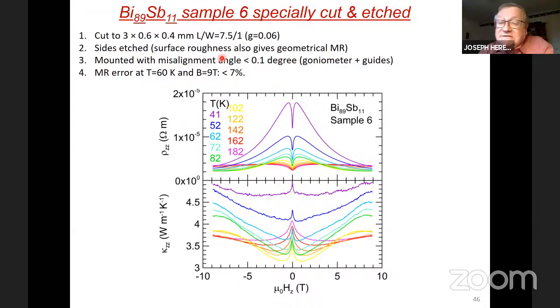And so our little error estimation routine then gives us at 60 Kelvin an error that is of the order of 5%, certainly less than 7% would correspond to this, which is a worst case scenario. And then he managed to measure on the same sample the resistivity and the thermal conductivity, so that we can now make a direct one-to-one comparison, this to that, and get the Lorentz ratio.